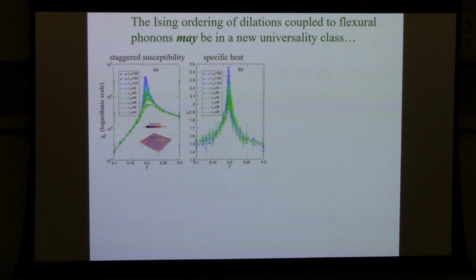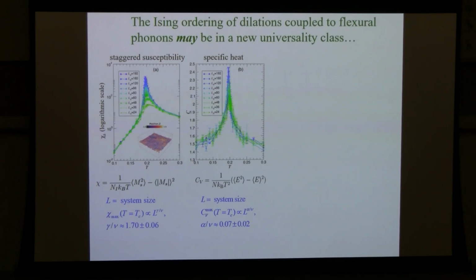Okay, so let me finish up by just summarizing our conclusion for this mechanical analog of an Ising antiferromagnet riding on a background of phonons. This is the susceptibility, the response function for the staggered antiferromagnetic order. It seems to diverge in a way that varies in a sensible, understandable fashion with the size. This is the specific heat. And then we can look at these exponents. And so here's our susceptibility. There are standard finite size scaling tricks for getting these Ising exponents out.